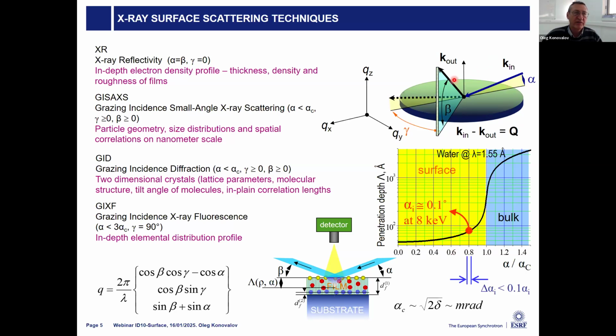So this is the geometry: we have a surface, and a beam which goes at a very shallow angle to the surface, and afterwards we scatter. By changing this angle or working below the critical angle, we can probe only the very top layers of the system, and in this way we can see what is going on at the surface compared with the bulk. But of course, if we have something deposited on any type of substrate, with the same technique we can probe only this film. Playing with the difference in the scattering or critical angles, we can magnify the intensity from the surface.